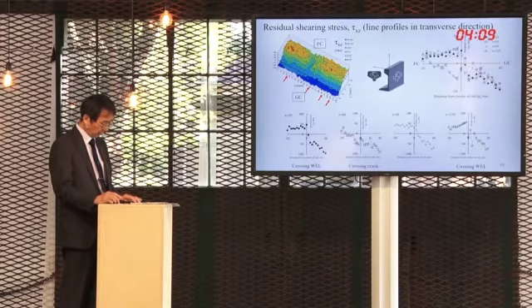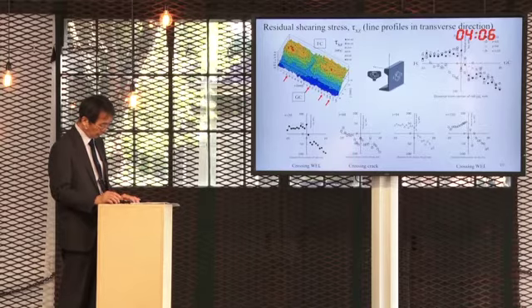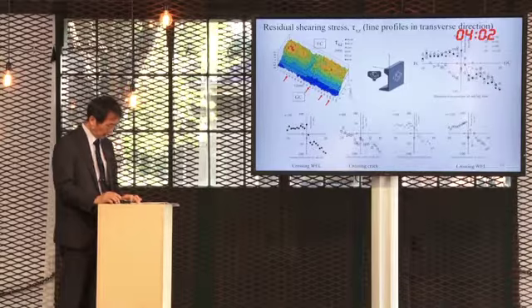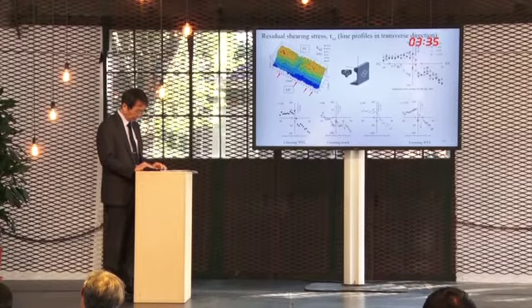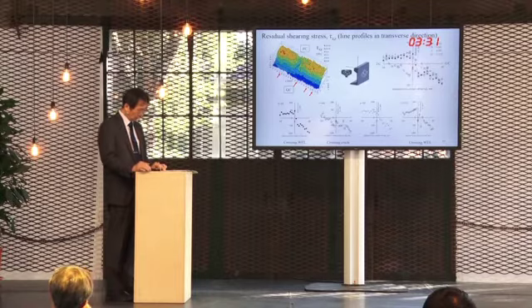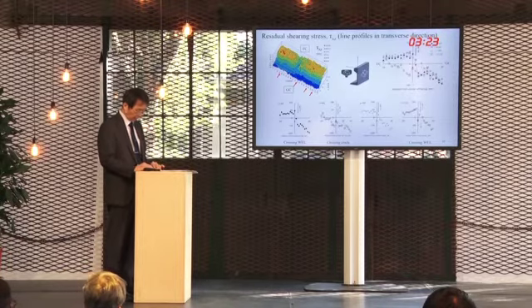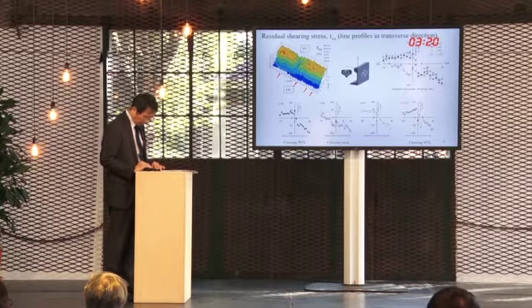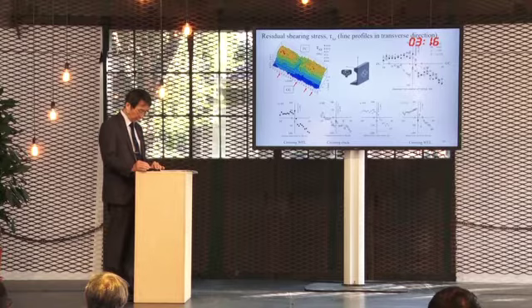Line profiles of tau xz are shown in this slide. 4 lines were selected and compared. The first line and the fourth line cross over the white etching layer. The second line crosses over the crack. The third line crosses the area without white etching layer and crack. As a result, similar stress distributions are seen in the result except for the second line. In the second line, it can be seen that the stress is relaxed or has negative values on the gauge corner side. This change is thought to be due to the occurrence of the crack. Whereas it seems that the change is small at the field corner side.